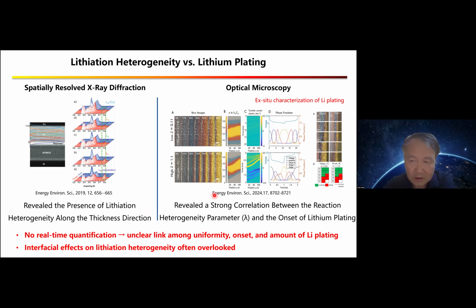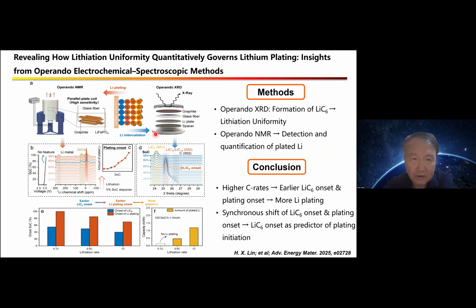Nearly all of the results presented here are mostly ex situ techniques, so it's hard to look at the real situation of the graphite cell. In this work, we use two operando techniques to monitor the lithiation of graphite and the formation of lithium metal. For operando XRD, it's hard to see the formation of lithium dendrite, but it is sensitively probed by operando NMR. So we combine these together to see what happens at different charge rates.